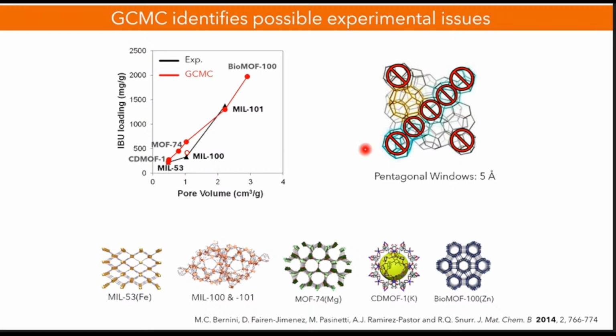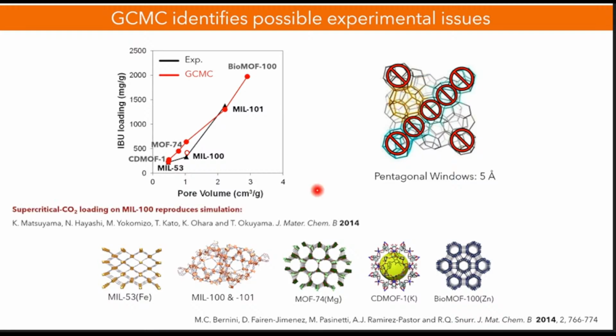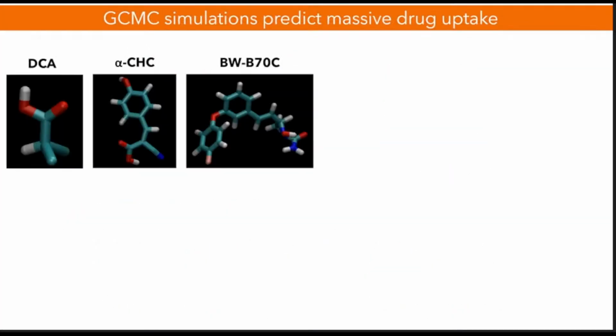And this is basically suggesting that in the experimental work that was published a few years before us, they were not exploiting all the capabilities of the material. They were just exploiting the bigger cavities that are here. This is important because after we published our paper, there was an experimental confirmation that you can really reach this loading capacity when you have this supercritical CO2 loading. They also cited this paper, saying yes, we were able to reach the values that were predicted by the original simulations.